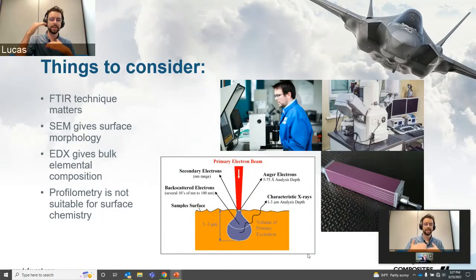But again, you're getting like 2 microns down into the surface. You're ignoring that actual region that you care about a lot. So many times when we've gotten into troubleshooting situations on adhesion production challenges, the engineering team will say, well, we tried EDX, but we couldn't see anything. We couldn't distinguish. It just looked like aluminum. And that's because we were getting down too deep.